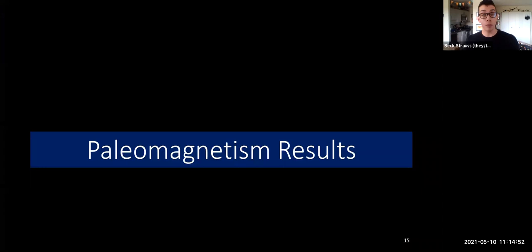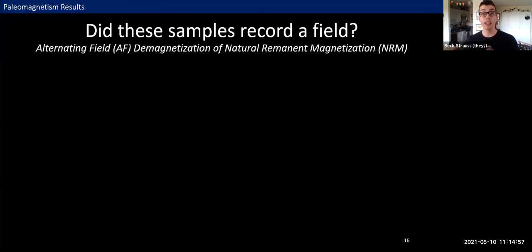So I'm going to jump into our paleomagnetism results. The first question we asked was, did these samples record a field when they formed? The experiment that we ran in order to determine this was an alternating field demagnetization of natural remnant magnetization, which means we applied alternating magnetic fields of progressively stronger intensities to stepwise remove the magnetization that the samples walked into the lab with, essentially rewinding the process by which they were magnetized.